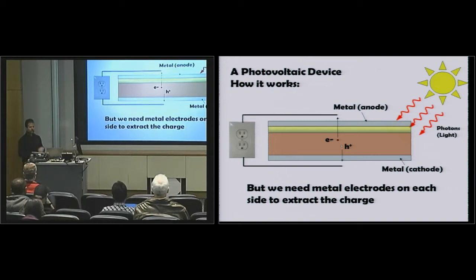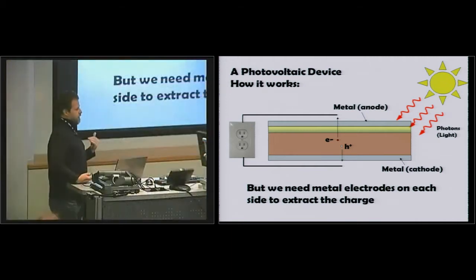But then on the other side, you have a conducting material that's transparent, and those tend to be transparent conducting oxides, or TCOs. So when people are talking about photovoltaic devices, especially thin film photovoltaics, they'll mention the TCO layer, and that's one of these electrodes that has to be electrically conductive, but it also has to be transparent. And for some devices, that TCO layer can actually be what's limiting the device efficiency. If you want to eke out a couple of extra percent, you have to change the TCO. So these electrode layers are also really important. If you have the wrong metal on one of these sides, you can create electric potentials that actually prevent electron and hole injection into those layers. So those are really important.